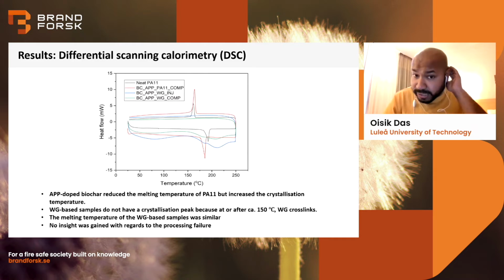And for the gluten, there was no change in the melting temperature, and because gluten acts as a thermoset plastic, after 150 degrees centigrade, there was no crystallization peak. However, from the DSC analysis, we did not gain any insight regarding why the compression molding of polyamide 11 and the injection molding of gluten with APP doped biochar was not able to form the samples.